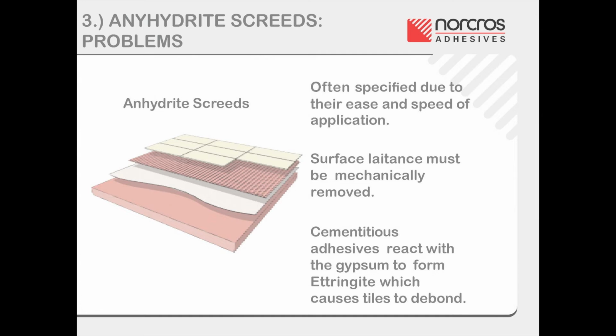When preparing the screed, the laitance must be removed 2 to 6 days after it has been laid, although this is dependent on the brand of screed used and should be advised by the manufacturer. Ensure the floor is completely dry. The residual moisture should be less than 0.5%. Again, the total drying time of the screed will depend on the brand used. Before commencing, ensure that the surface of the floor is thoroughly clean and debris-free, as with any other application.